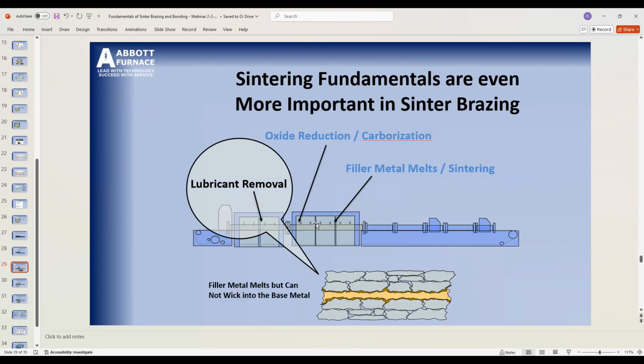Okay, so here we can say it's really important for us to remove the lubricant. Now, we have to remove the lubricant in the right way, though, because if we heat up too fast and that lubricant comes to the surface and it comes into our gap and it dissociates, we're going to form dirt. We're going to form soot, and then we won't bond because the filler metal won't flow in there. So in this process, in the sinter brazing process, lubricant removal is critical.